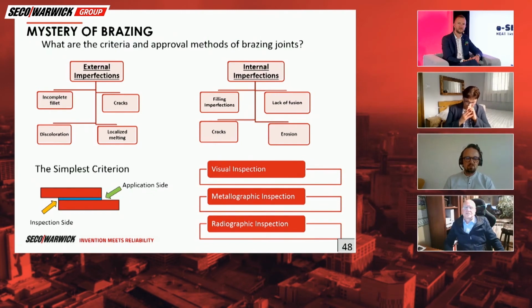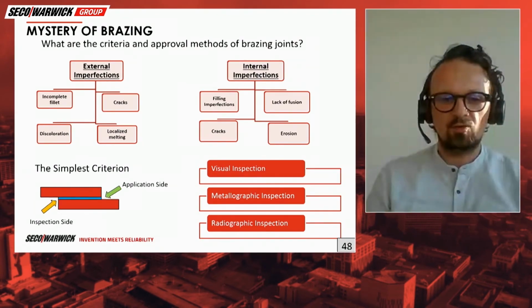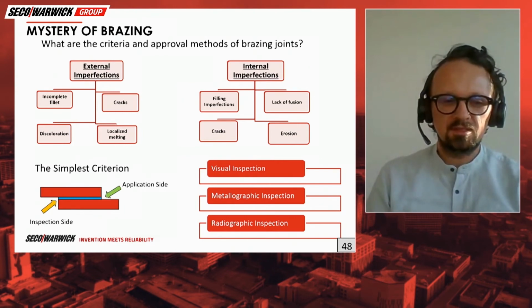You could go deeper into that and see what's the type of the joint, if it's an overlap joint, what kind of overlap we have, if it's 3 times the thickness, 6 times the thickness, and set up the criteria against that, and what's the strength we require. Lack of fusion, obviously, is no-go, because if you have oxides on the surface, as Leszek mentioned, we might see lack of fusion, because the braze alloy won't spread on the surface, and there is no stickiness. Cracks, obviously, that's no-go, and erosion, it depends.